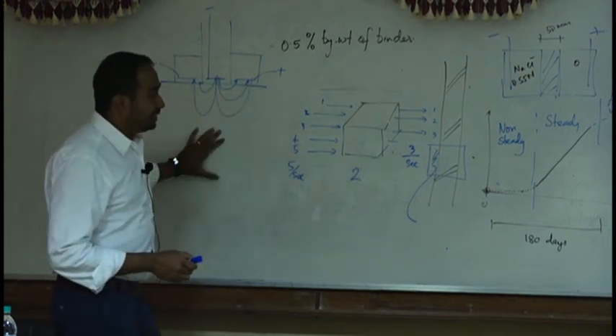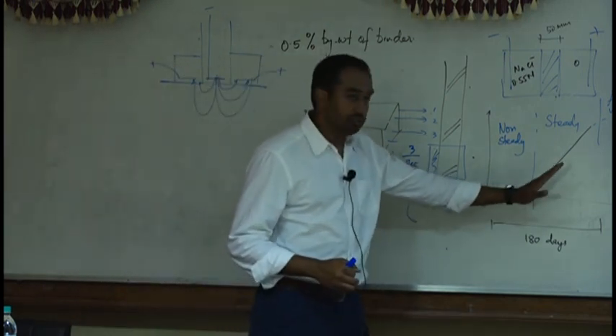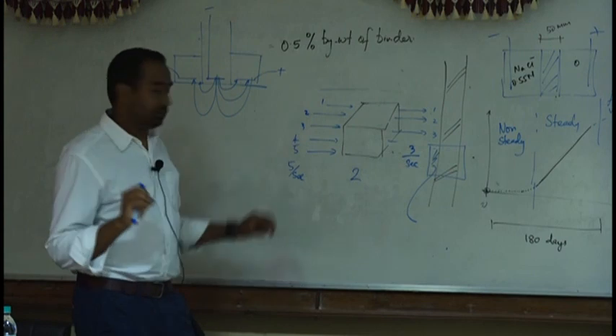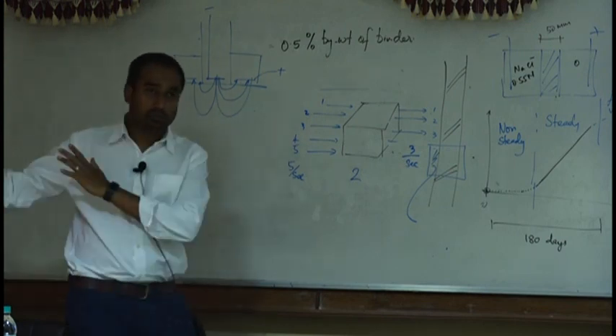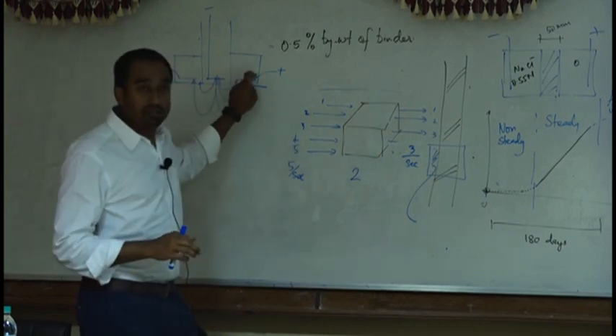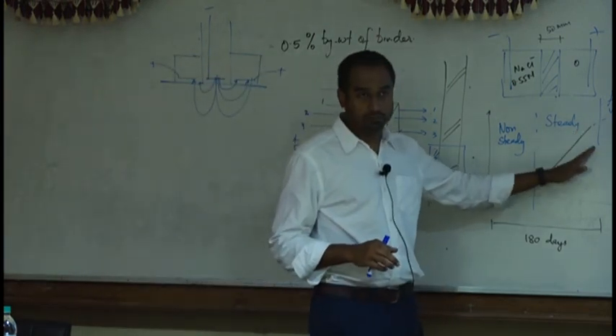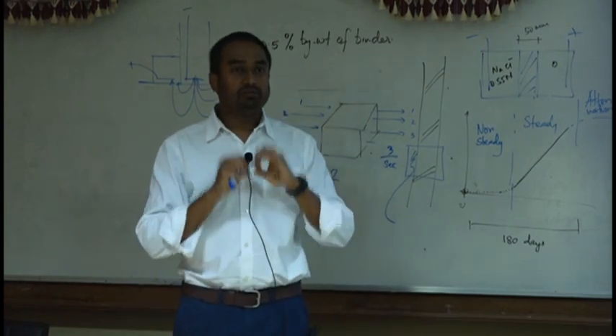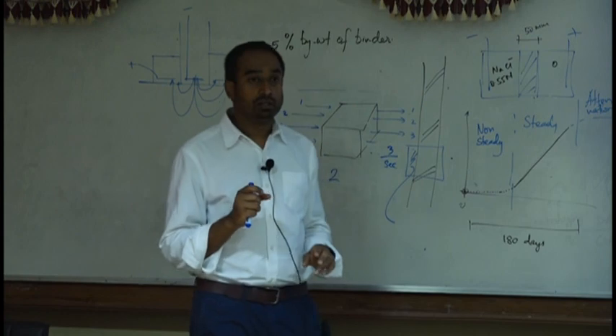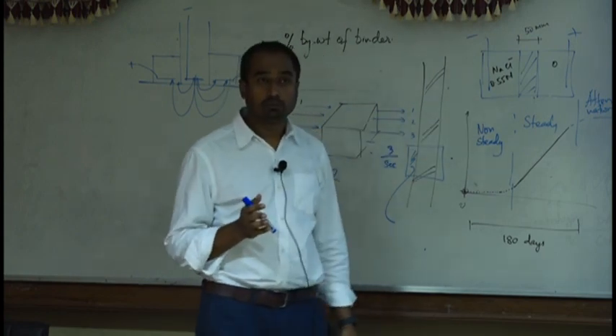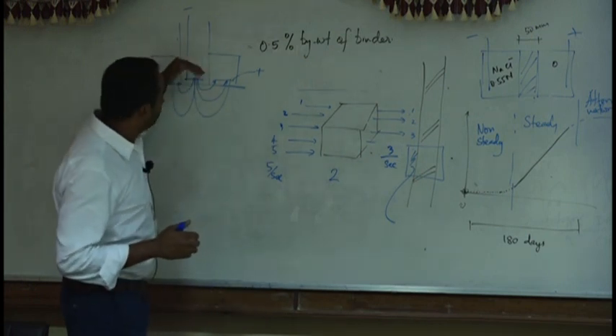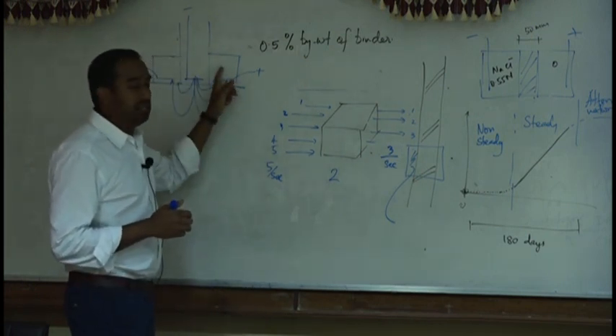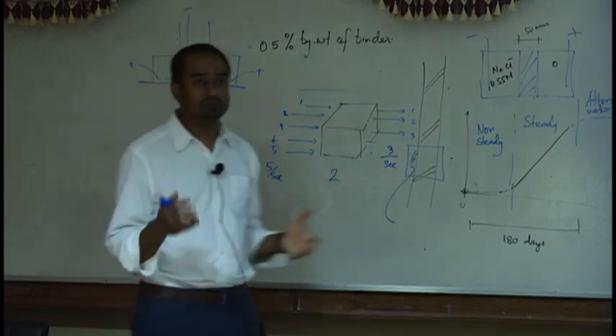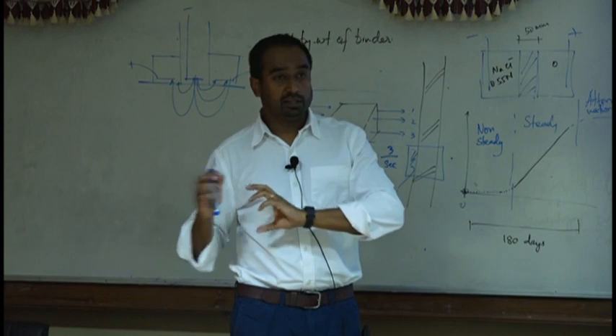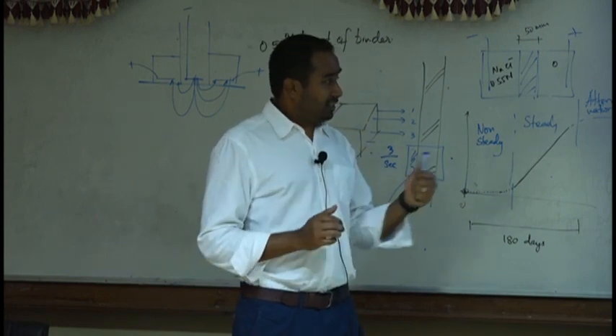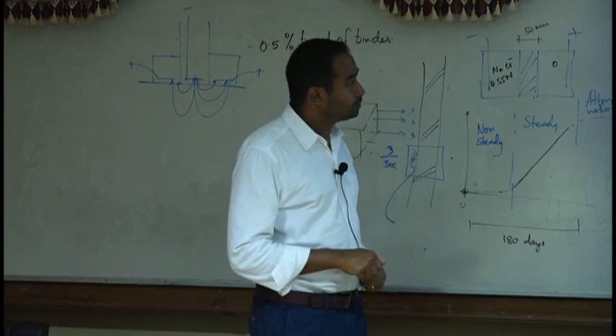Okay? So in this test, what you're getting is very similar to that result, but it is a pseudo result in the sense some of the chlorides will go out and out. But because I'm only looking at what's coming here, I will get a very similar curve. But the slope that I get will be much smaller than if I use that kind of test. That is to do with the fact that I may have 100 chlorides going out, but it's only 80 of them coming back steady, so I'm losing 20 of them in the flow. Okay? But that's okay because I'm looking at the steady state part of it. So that's permitted. Any questions?